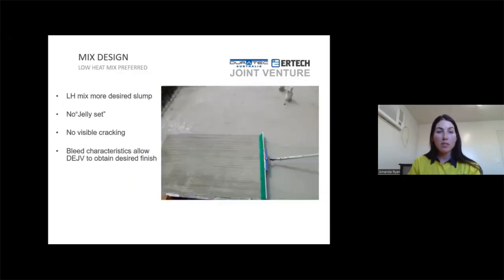This was the mix without silica fume. So this low heat mix definitely had a desired slump. We exhibited no jelly setting, no visible cracking, and the bleed characteristics allowed DEJV to obtain a desired finish. It was easier to trowel and easier to broom, which is this photo here, a broom finish, which is the requirement for our slab.